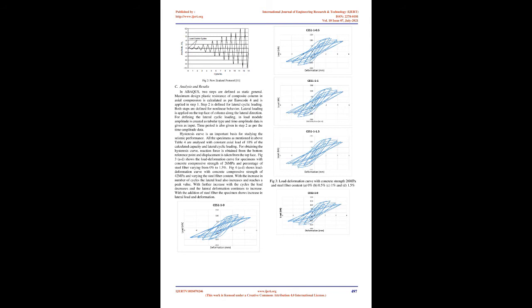As per the protocol, the first 3 cycles are load controlled. Lateral force equal to 50% of the theoretical force is imposed during the first 2 cycles of loading. First yield displacement is determined in the 3rd cycle. After that, the subsequent cycles are displacement controlled.